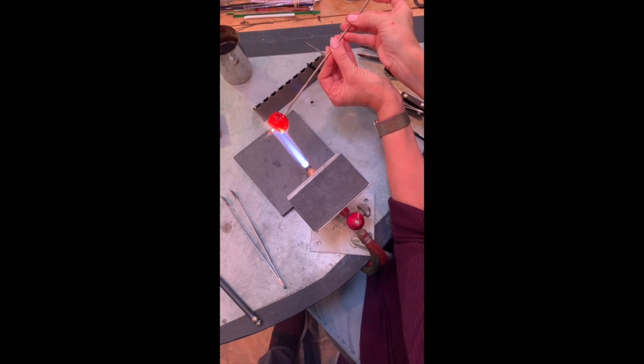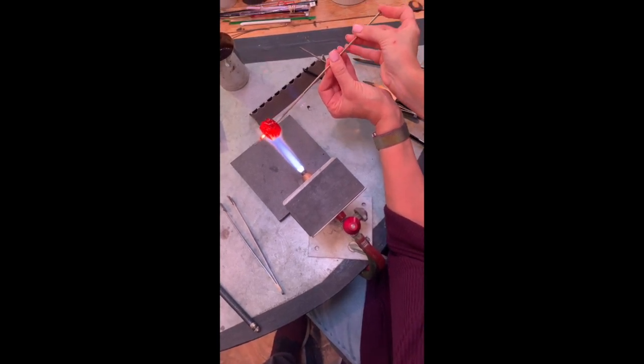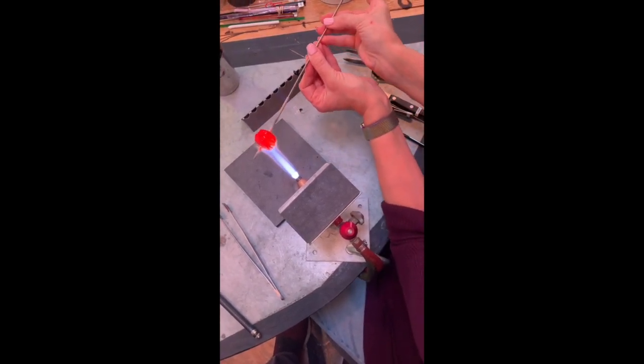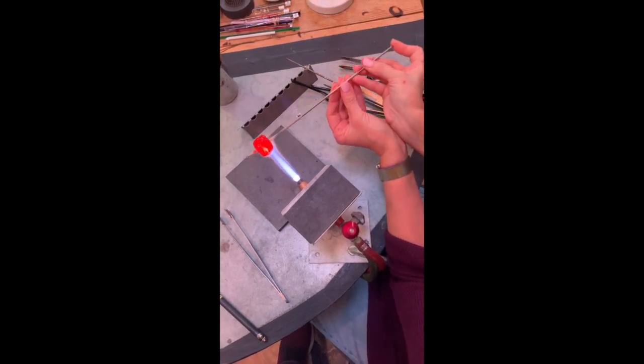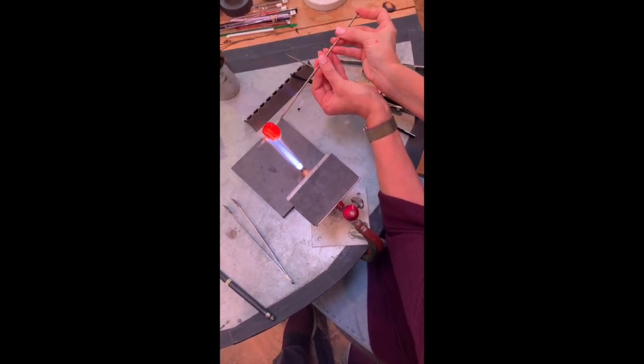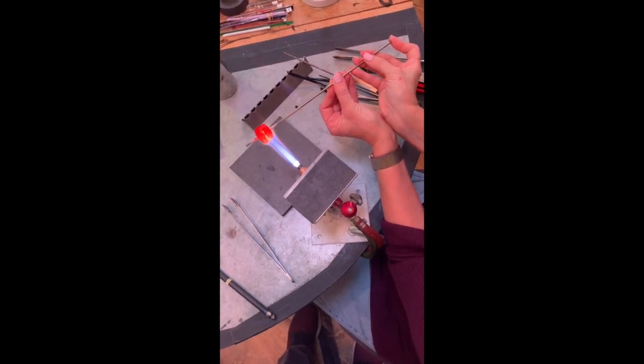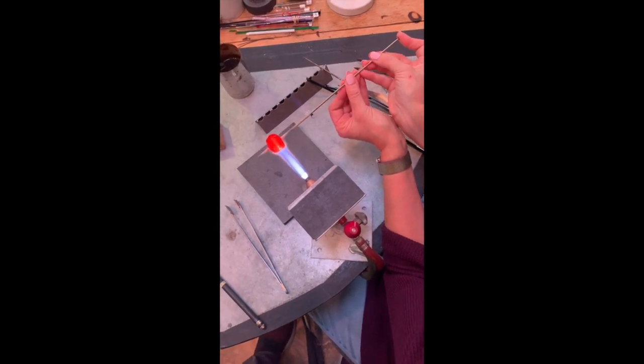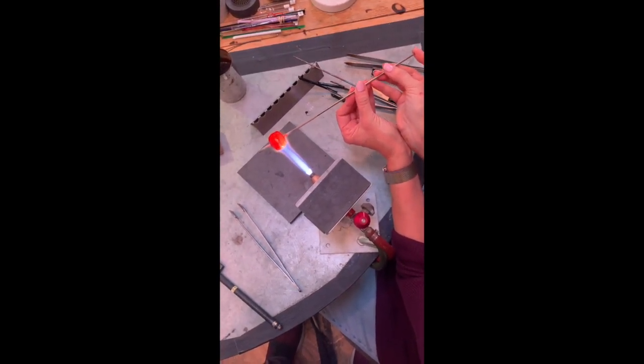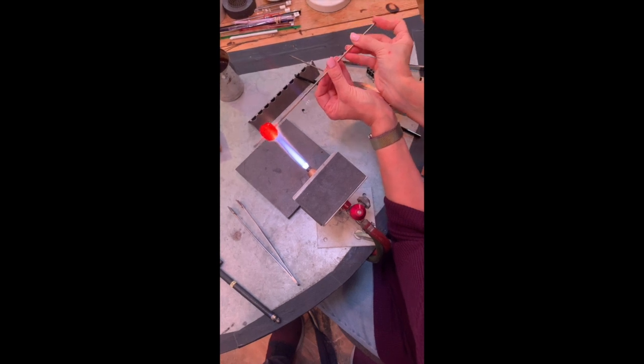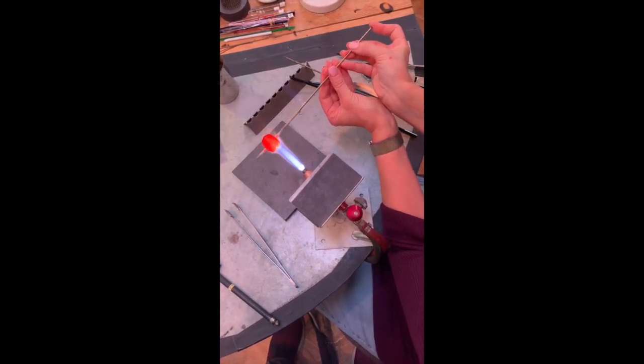So I'm taking the time to slowly heat the entire bead. And now I'm going to tell you what's going to happen, because once this is in my mouth, I can't really tell you. I'm going to let this become a molten hollow bead that will look just like a hollow bead made on a regular old mandrel. I'm going to keep rotating it. I'm going to bring it up to my mouth. And while rotating it, I'm going to give it a gentle blow. And as I watch it expand and stiffen up—and I can see all that because I can just look straight down the mandrel from my mouth toward the end where the bead is—I'm going to sort of slow down my blowing, because you don't want to